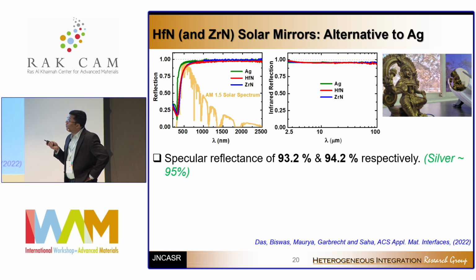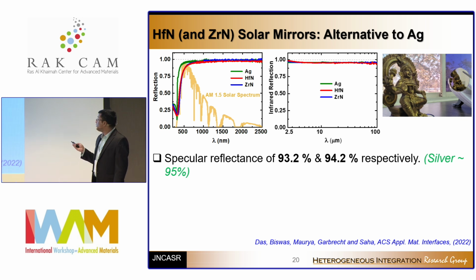You see the green one is basically the silver, and this hafnium nitride and zirconium nitride are pretty close to silver. And that's exactly the reason why silver is still the best, 95% of the solar reflector, but hafnium nitride, zirconium nitride, they show 93%, 94% solar reflection, which is pretty good and pretty large.